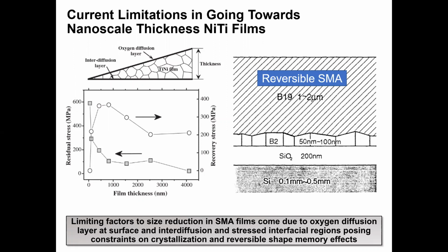Grain size is also a critical factor, where it's generally established that grains below 80 to 100 nanometers will not exhibit the martensitic transformation. And this is due to additional physical constraints imposed by the grain boundaries, and eventually the volume of the grain is too small to even support a reversible phase change.